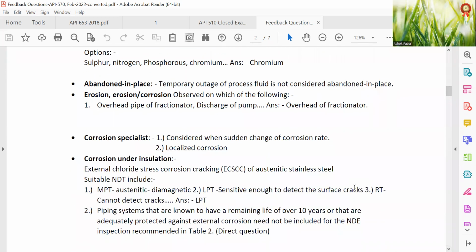Corrosion specialist is considered when there is a sudden change of corrosion rate, or localized corrosion. Corrosion under insulation and external chloride stress corrosion cracking, ECSCC, of austenitic stainless steel: suitable NDT method? MPT, austenitic is non-magnetic, diamagnetic. LPT is sensitive enough to detect surface cracks. RT cannot detect cracks. LPT. Piping systems that are known to have a remaining life of over 10 years, or that are adequately protected against external corrosion, need not be included in any inspection recommendation.